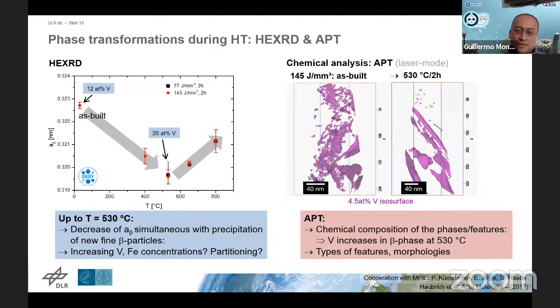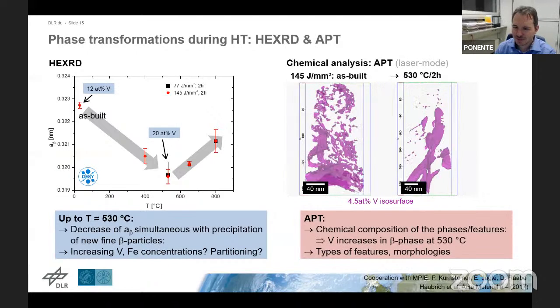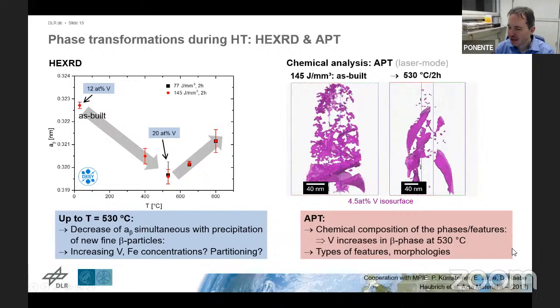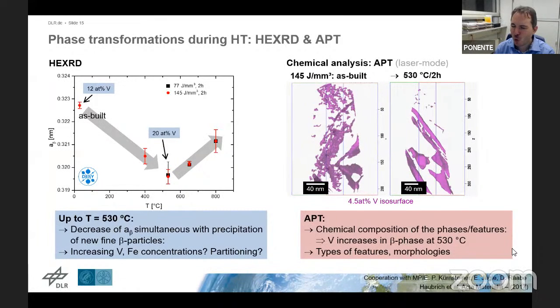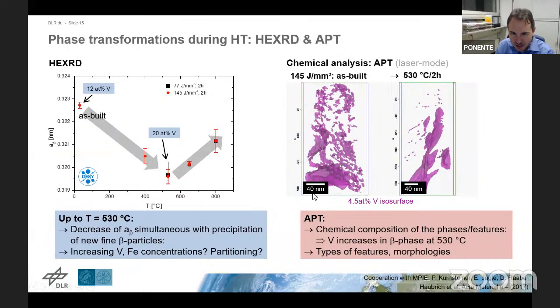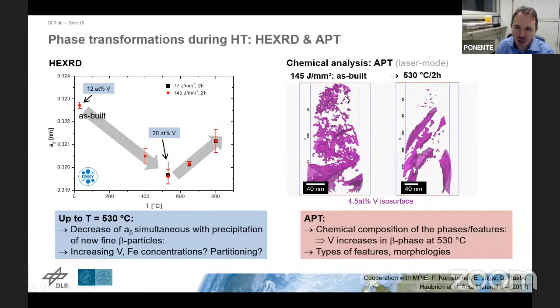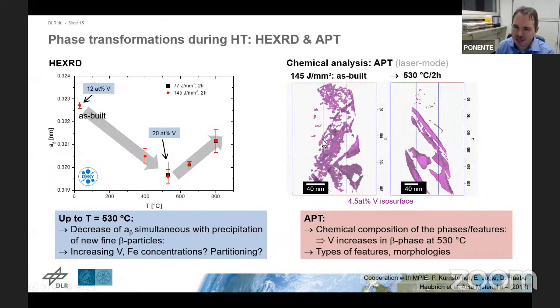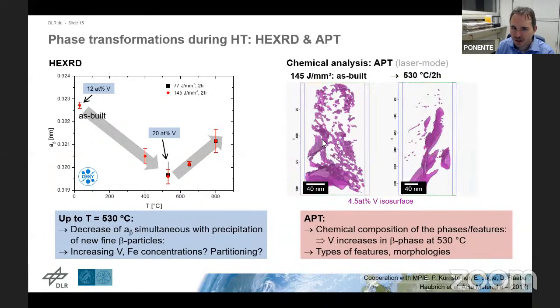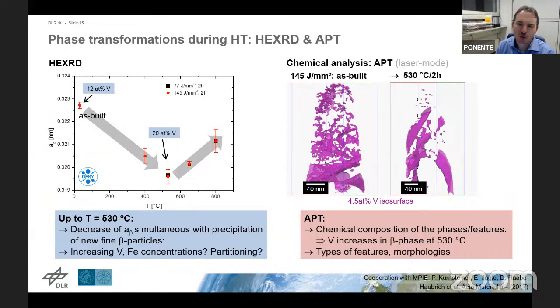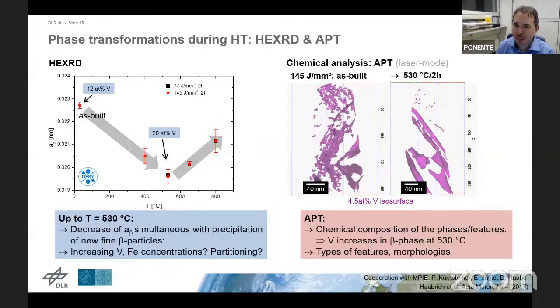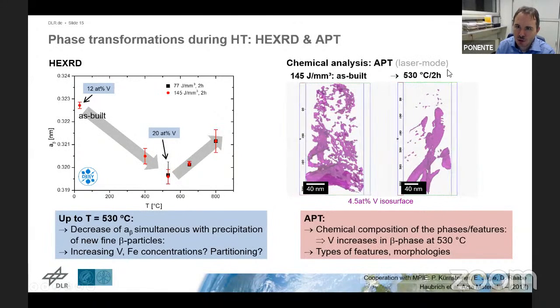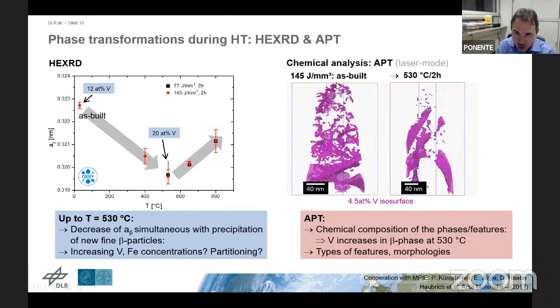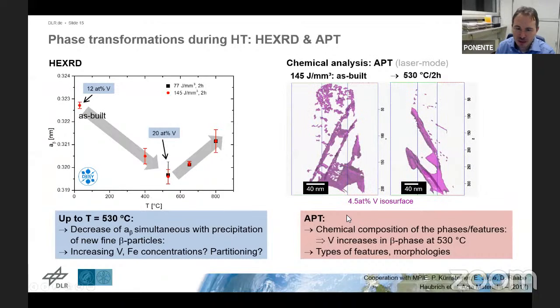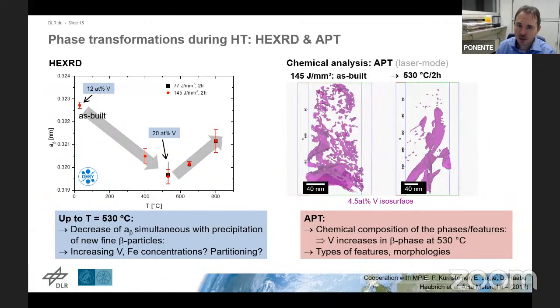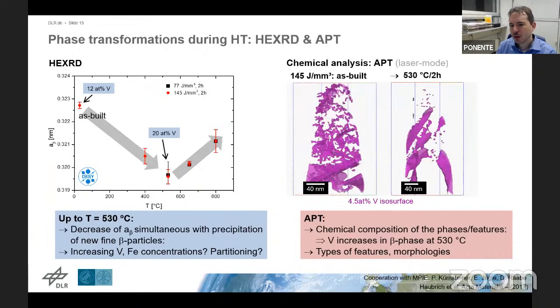That's something that our cooperators at MPIE next to us in Düsseldorf did, Philipp Kürnsteiner, Erik Jägle, and Dirk Raabe. So as you described, it's first by FIB, you machine a very small, very sharp tip with a base diameter of like 100 nanometers and a length of maybe 200 nanometers out of a specimen. That certainly takes a day, I would say, or half a day maybe per tip. Transfer them into the APT, which is an ultra high vacuum machine, basically with an energy source like a laser. In this case, the laser mode of the APT was used to evaporate the material of the tip starting from the top. And the material then dissipates in the vacuum, and there is a mass spectrometer that tries to measure the atoms that are atomized there. So it's a very tricky technique.